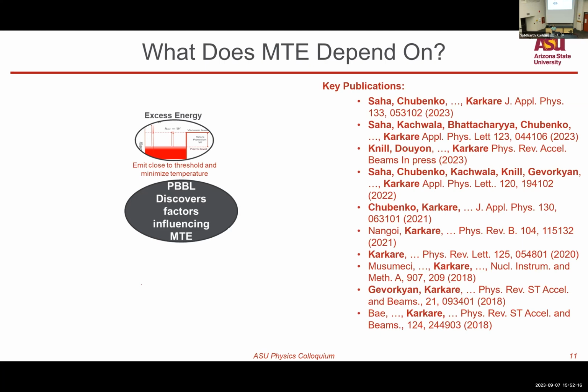It's the energy difference between the photon energy and the work function, or really the excess energy that the photon provides the electrons above the work function. When they get emitted with this excess energy, they have the kinetic energy of photon energy minus the work function, or that's the maximum kinetic energy they can have. Some part of this excess energy gets converted into the mean transverse energy. So reducing mean transverse energy is very straightforward to do. Just change the wavelength of your laser to match it with the work function.